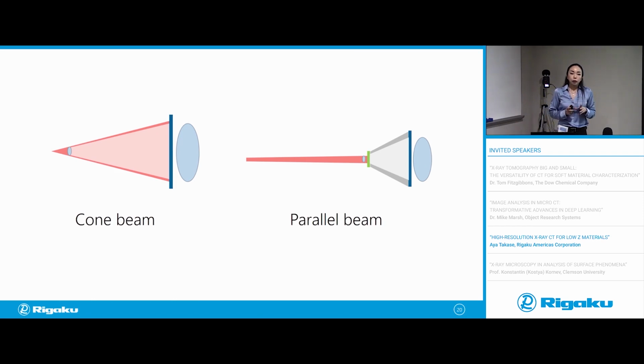Now, cone beam geometry is a versatile and very convenient geometry to use. But as Tom was mentioning this morning, because of the source size and drift, the source could drift if you do, especially, 5 hours, 10 hours of scan, and you're trying to keep this 5 micron size focus in one place. That's not a trivial thing to do. It would move sometimes, and the size is limited. And because we're using this X-ray beam divergence for magnification, whatever you have at the source gets magnified as well. Meaning that if the source drifts, that drift is magnified by the beam divergence, and that means you're going to end up having a blur image.